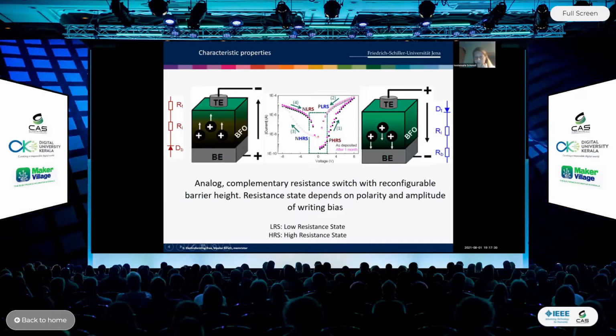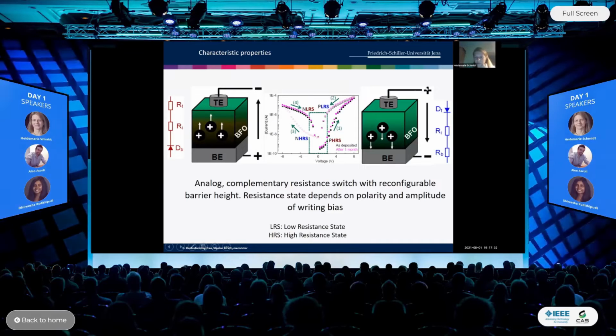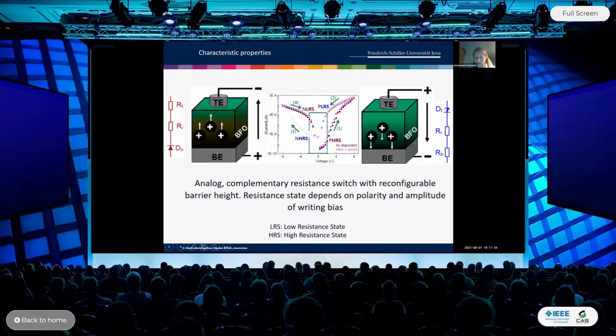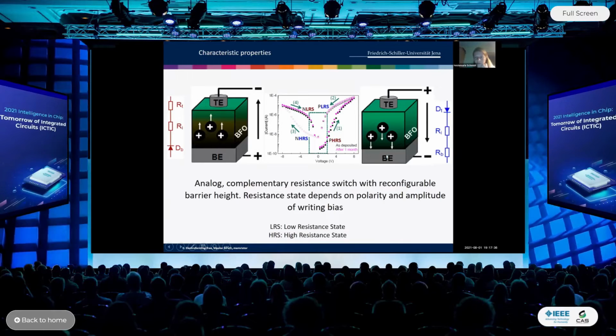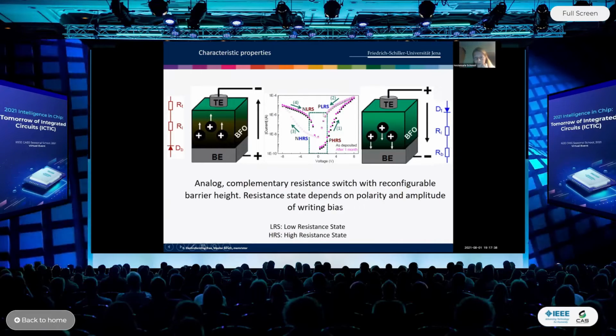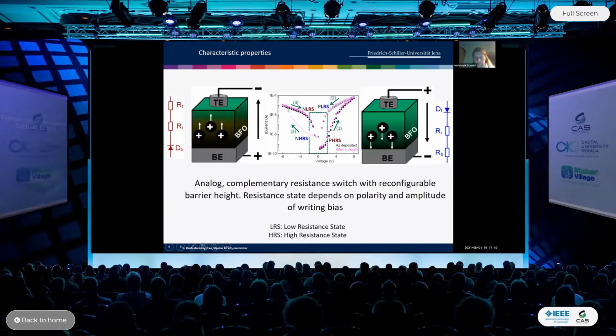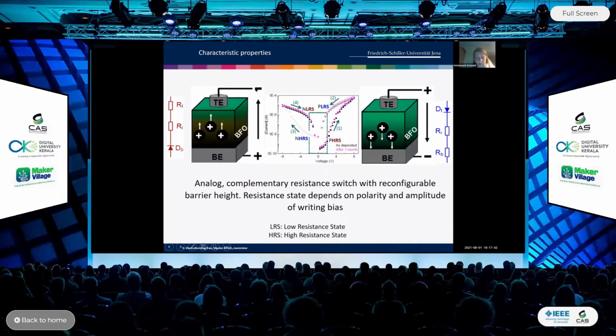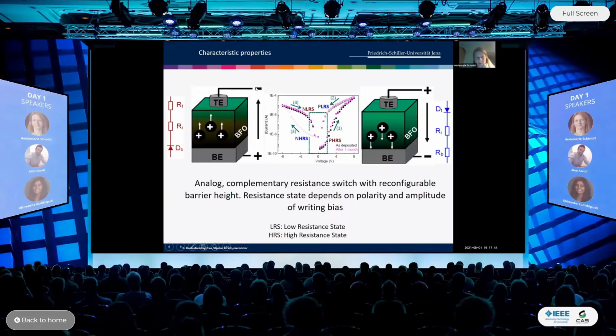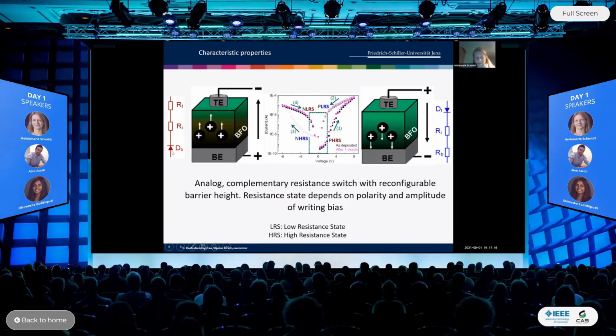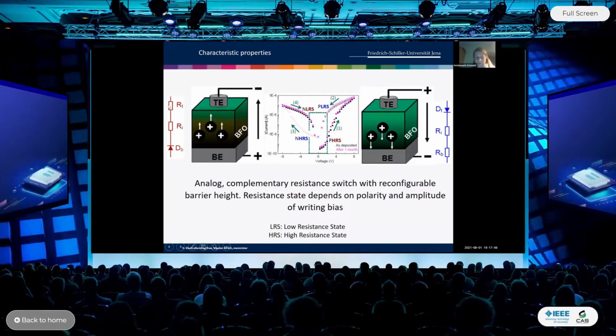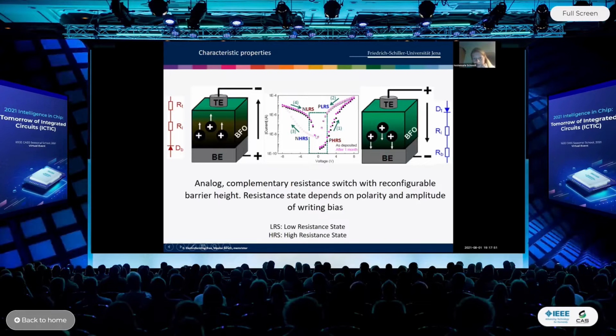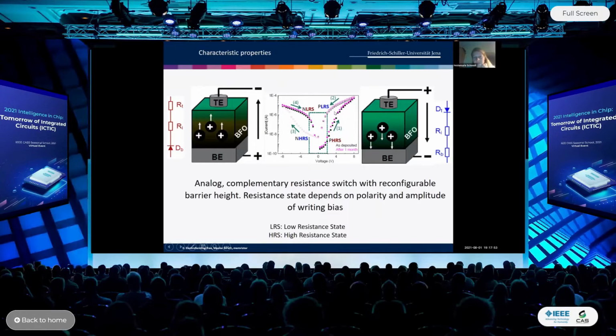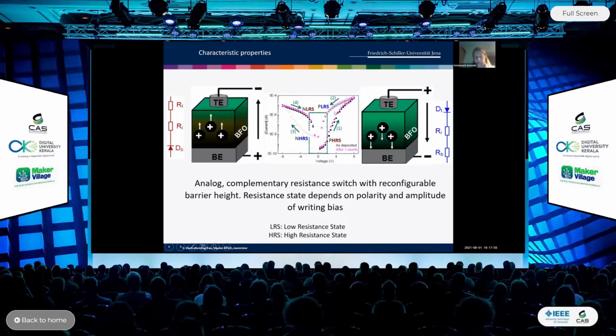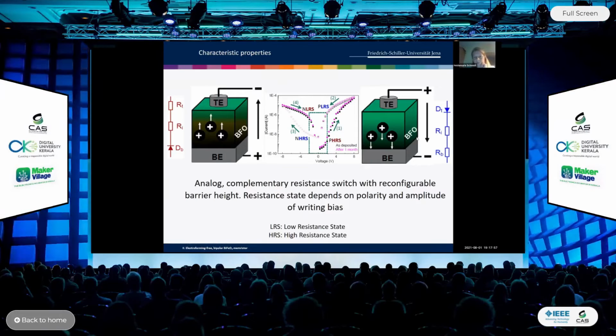For example, if we apply a positive writing bias, which is the case here, then the top electrode is rectifying, the bottom electrode is non-rectifying, and we see this characteristic curve. And if we apply a negative bias to the top electrode, the bottom electrode is rectifying and the top electrode is non-rectifying, and we see this characteristic curve. That means the polarity of the writing bias determines which curve we see.